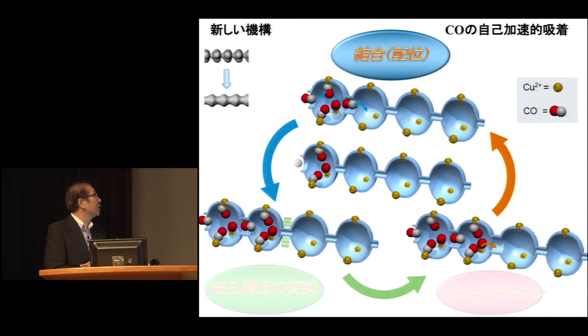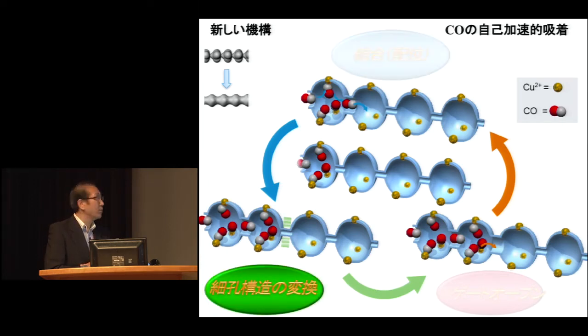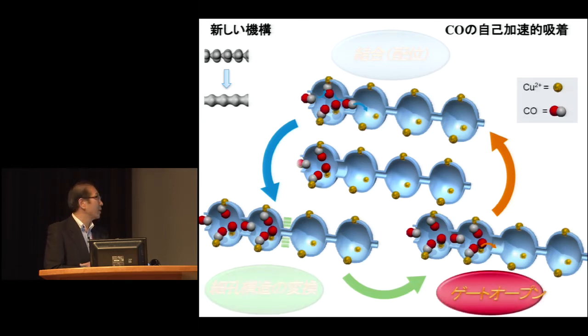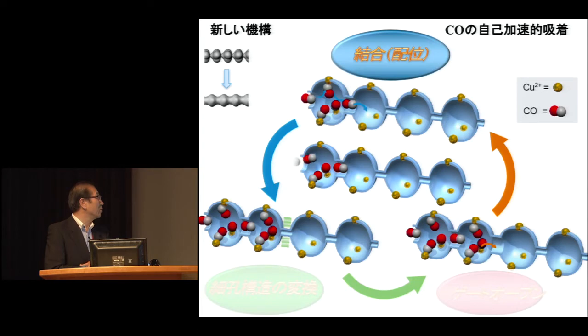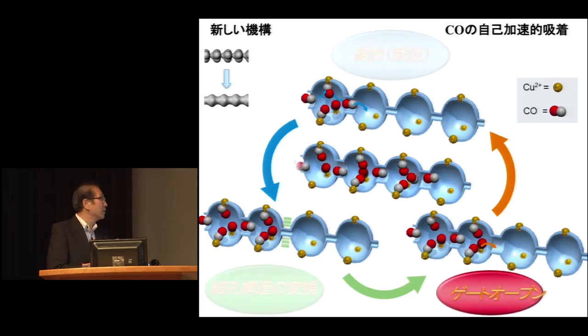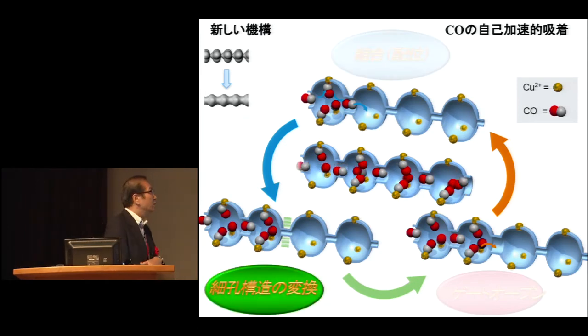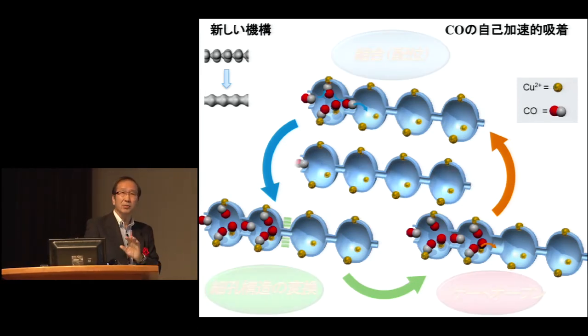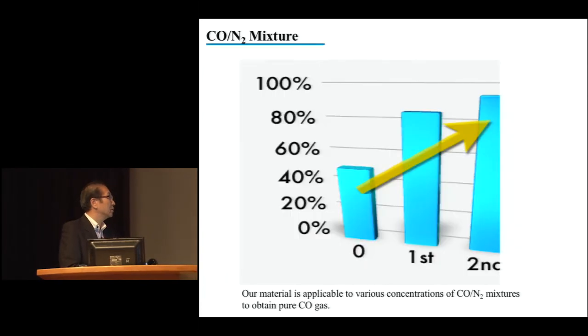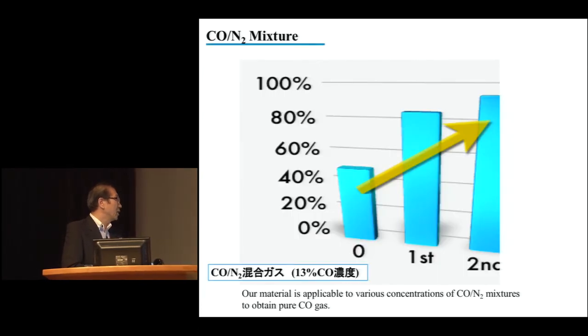These are the channels in the structure. This is a copper ion, and CO is bonding, and N2, nitrogen, cannot bond. And when there is a bonding with a CO, then the next gate opens, and this CO comes into the next space. This one is already crowded, and N2 even cannot come in. Only CO is allowed to come in. So this is a way to accelerate the absorption of CO. So this material only recognizes CO but does not recognize nitrogen.